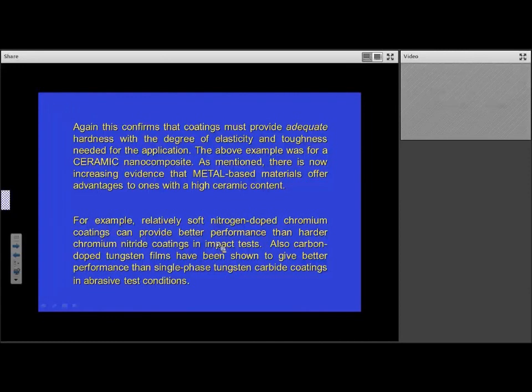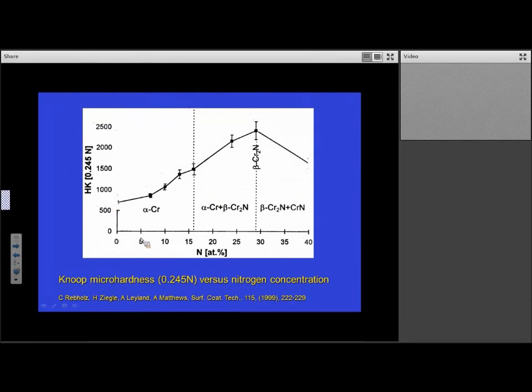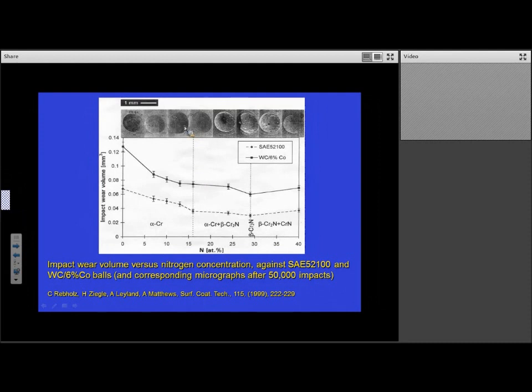So, for example, a relatively soft nitrogen-doped chromium coating can provide better performance than a harder chromium nitride coating in impact tests. Also, carbon-doped tungsten films have been shown to give better performance than single-phase tungsten carbide coatings in abrasive contact conditions. So just to illustrate this, if we've got a chrome coating and we add nitrogen, and we look at the hardness, the hardness increases as we interstitially harden. Then we put more nitrogen in, we get more of the ceramic phase, more Cr2N and CrN. And then if we do an impact test on these, the coating that performs best is the relatively soft but elastic interstitially hardened chrome rather than the very hard chrome nitride.